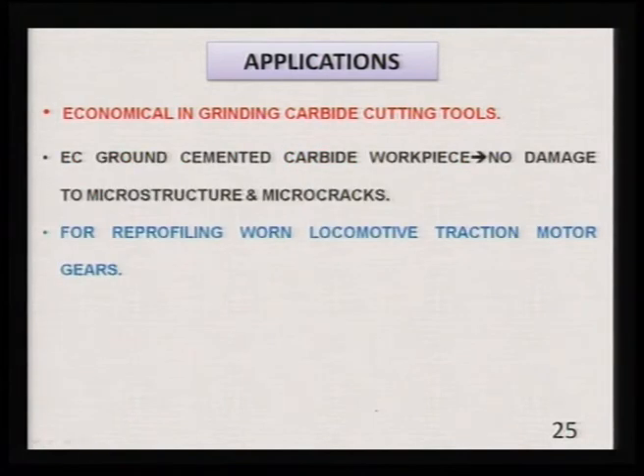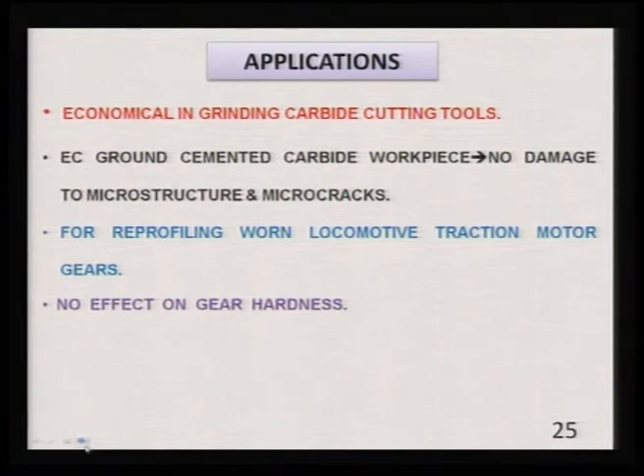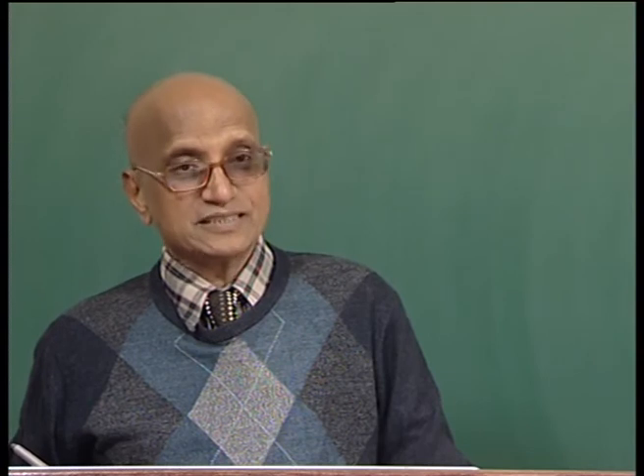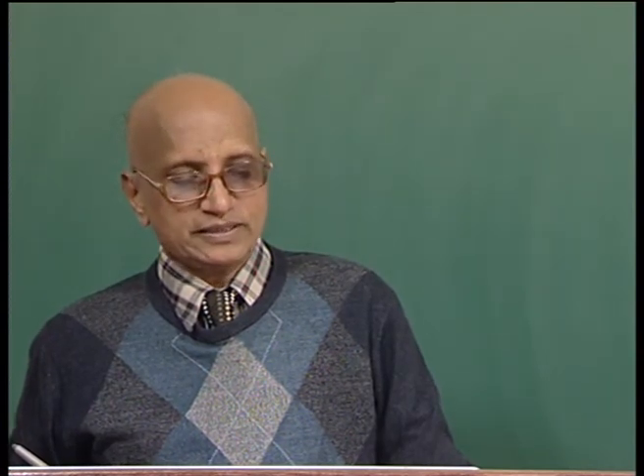Economical grinding of carbide cutting tools. Electrochemical ground cemented carbide workpieces have no damage to the microstructure, and hardly any micro cracks are created. For reprofiling worn locomotive traction motor gears, this particular process has been used. There is no effect on gear hardness when you are grinding or finishing the gears by the electrochemical grinding operation; hardness is not changed.